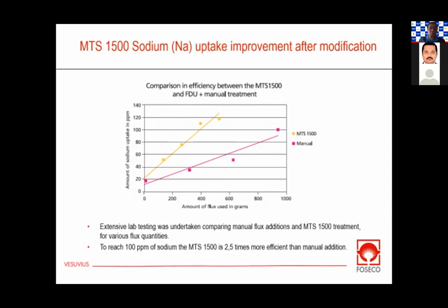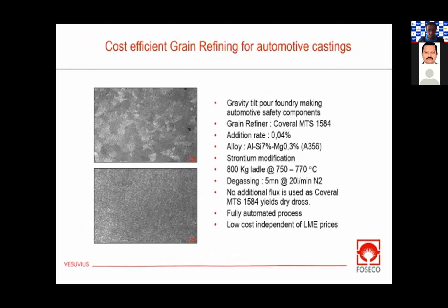Now, this means either better quality for the casting, less shrinkage, and a much finer eutectic structure, or it means less sodium use, so a lower cost for the foundry because they can reduce the addition rate of the sodium or the sodium flux. So again, this has been an important breakthrough for us.